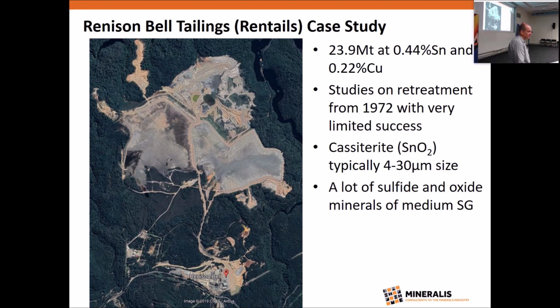After the start of the plant in the late 60s, they had a lot lower than expected recovery. And that prompted a search for ways, firstly for improving and secondly retreating the tails, and they always met with limited success. The main reason is the cassiterite in the tailings is typically very fine and well below the normal size range where you consider gravity processing a good idea. Plus the mineralogy includes a whole lot of sulphide and oxide minerals of medium to heavy SG. It's all dominated by pyrrhotite.